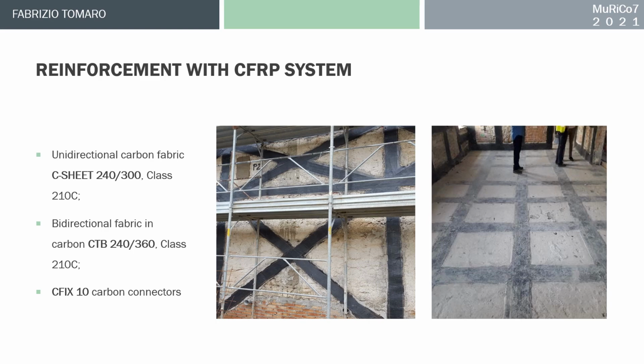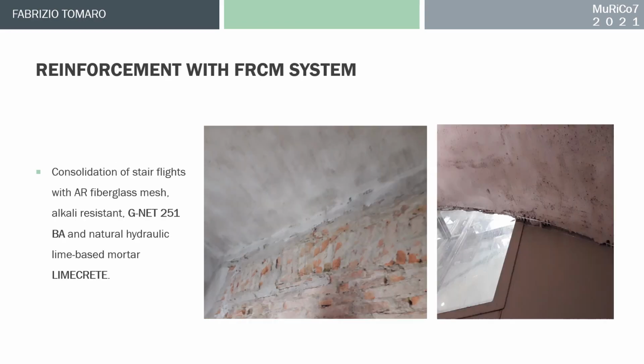To ensure a better anchorage of the fabric to the masonry support, in both systems carbon fiber connectors with a diameter of 10 millimeters were applied, embedded in the bearing masonry with epoxy adhesives. Finally, the consolidation of the flight of stairs was carried out using the FRCM system, fiber-reinforced cementitious matrix, characterized by the application of an alkali-resistant fiberglass mesh and M15 natural hydraulic lime-based mortar.